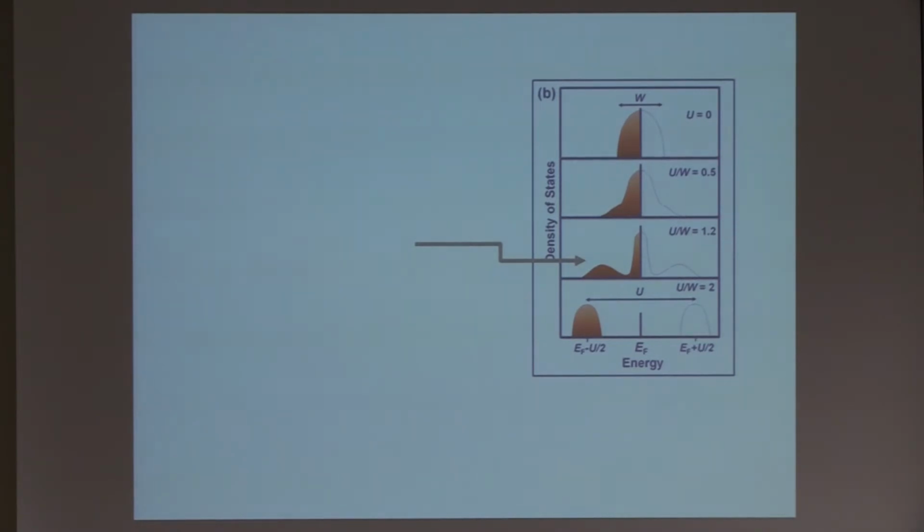Of course, there is a second feature right now. We were focusing very much on what happens in the renormalization of the bands at the Fermi surface. But there is this transfer of spectral weight, as the correlations get more and more important, to high and low energy, so away from the Fermi surface. And the question is whether this is possible to be observed experimentally. So in fact, the question is whether ARPES can observe this incoherent weight away from the quasi-particle peak.